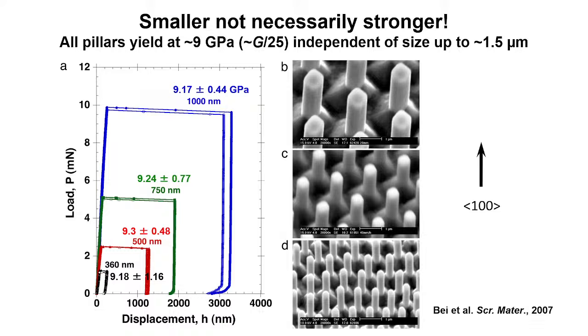So now we could take these pillars and extract them completely from the matrix. So now you dissolve the matrix away completely, and you're left with these very long fibers, right? And with the help of people in Germany, we were able to then test them in tension, not just in compression in the nanoindenter, but in tension. So this is what it looks like. You can pull on these fibers, and we saw something very interesting.